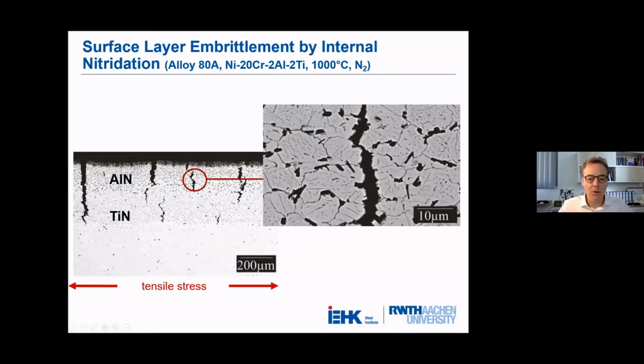And once we apply a tensile load in this situation, then we see brittle cracking within this near-surface layer. If we have a closer look, that is due to the complete coverage of the grain boundaries by internal nitrides.